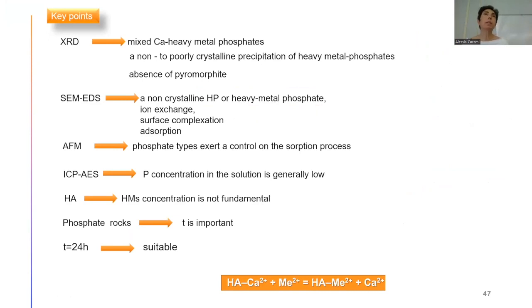At the end, we have this calcium metal phosphate. From SEM-EDS, we can decide for 3 different mechanisms, so it's not really useful as a way to study these materials. From AFM, we can say that the type of phosphate could exert a control on the sorption process. It's important to understand that changing the conditions of the experiment, in this case, can change the result, but the point is whether we can immobilize metals.